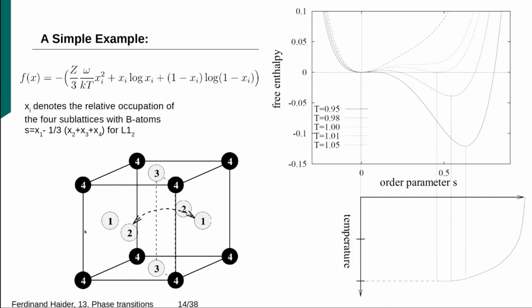Very much as before, you can use the occupation of these 4 sublattices with one species, the B atoms here, for example, at 25%. If all sublattices, in this case copper 3 gold, you have 3 copper atoms, so you put the copper atoms here on the face-centered sides and the gold atoms on the corner sides. Then you obtain a structure called L12.